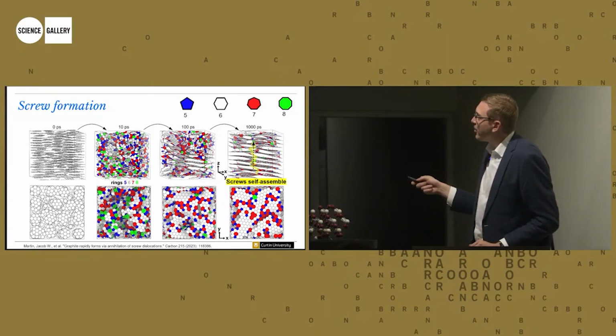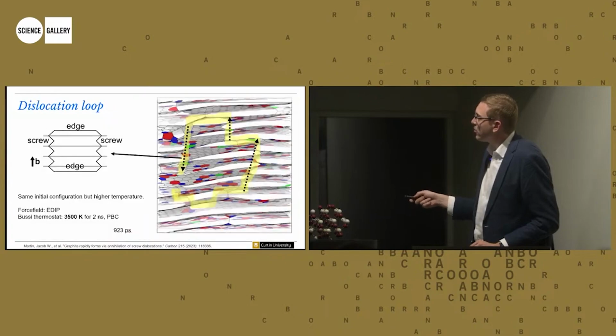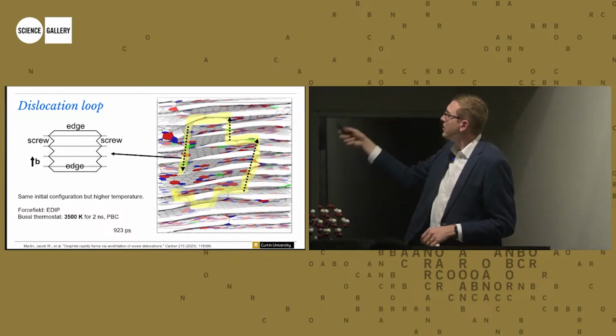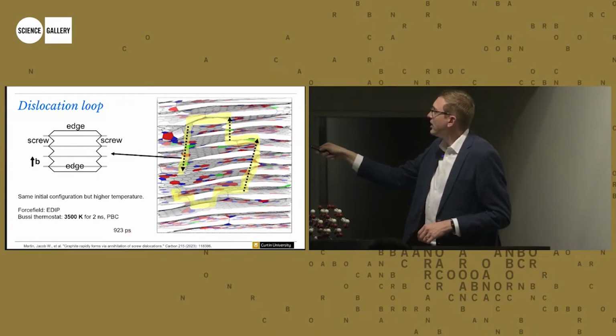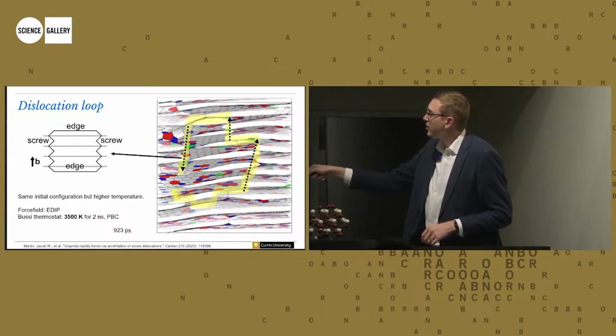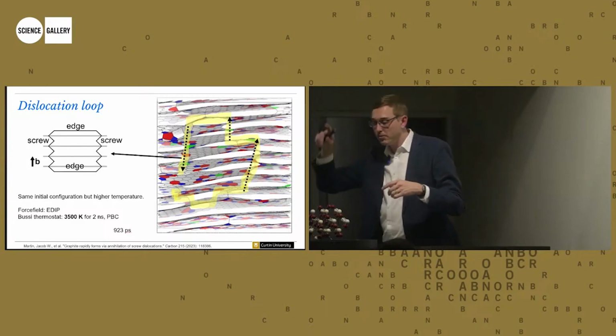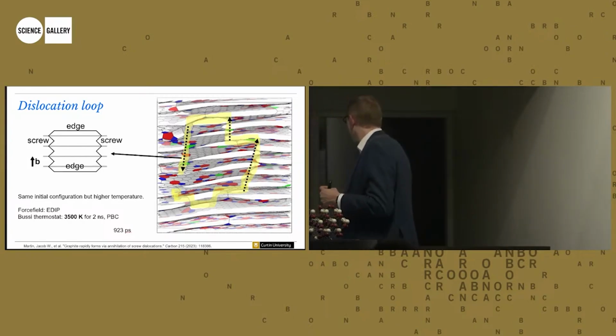We found that what happens is you form what's called a loop, a dislocation loop. So you have a right-handed screw, and then you have an edge, then you have a right-handed screw, then you have an edge, then you have a left-handed screw that kind of goes into the back there, and then you have an edge. And that forms a loop. Now I've actually, have I got one of those too?